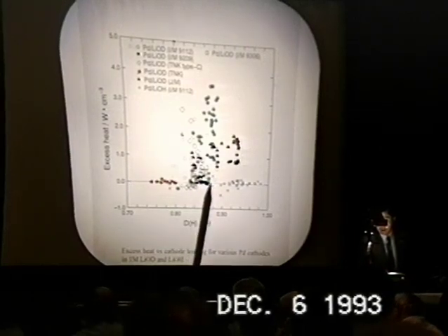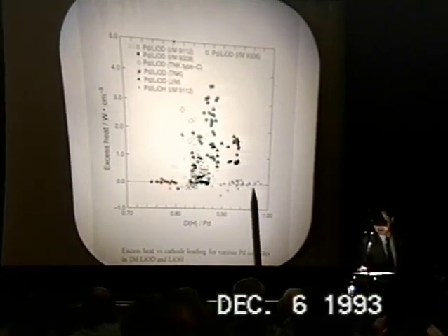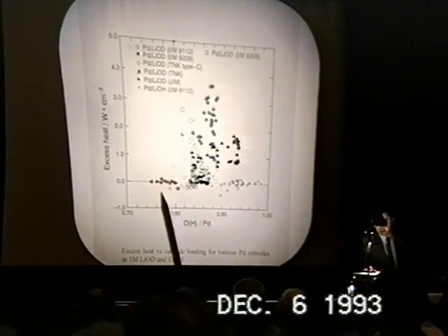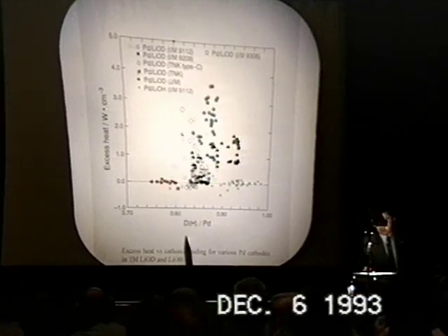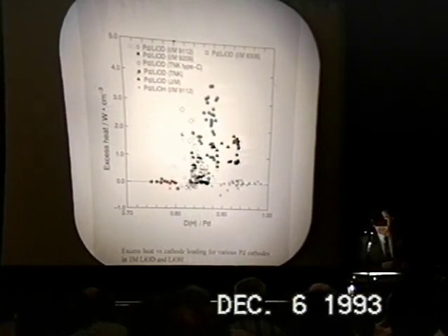So if you look at these data, the data points are rather scattered, but this part shows no excess heat for the light water system, and this part shows there is no excess heat evolution in the region of deuterium loading ratio below 0.8. And then after 0.8, 0.9 or so, we have some appearance of excess heat.